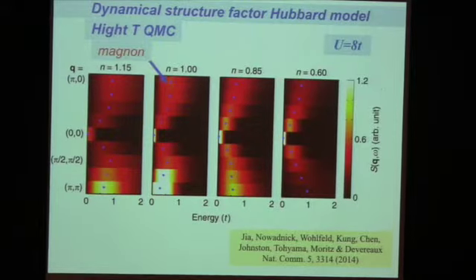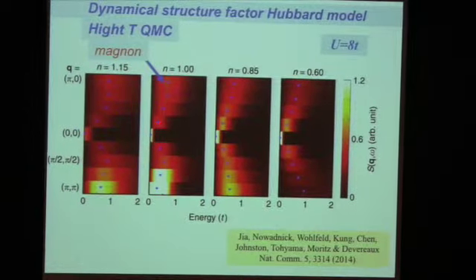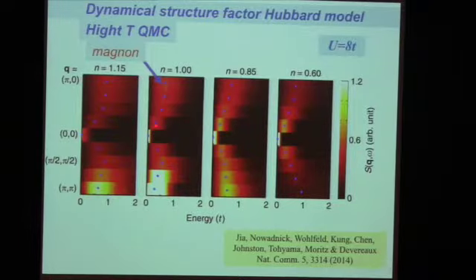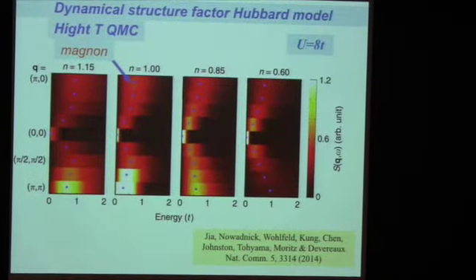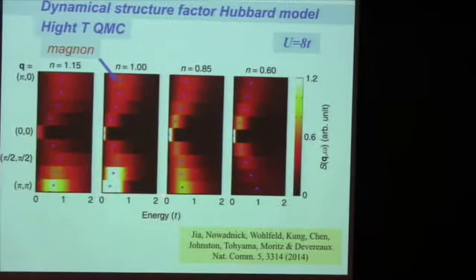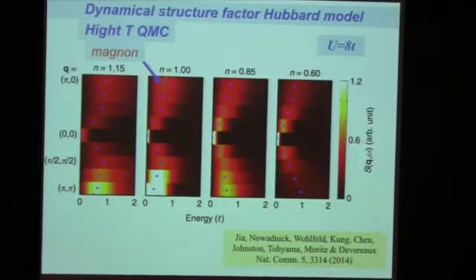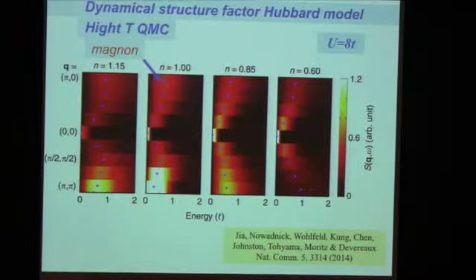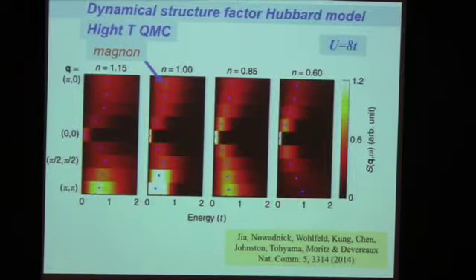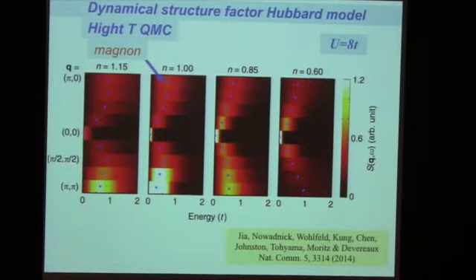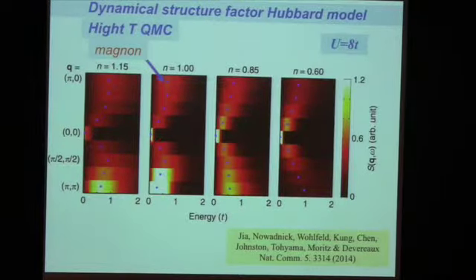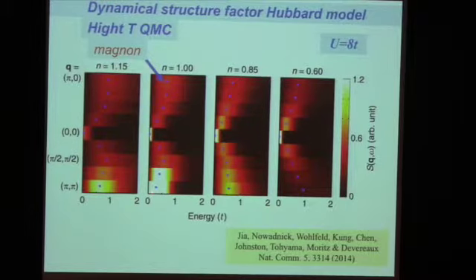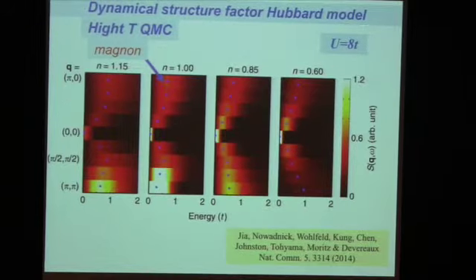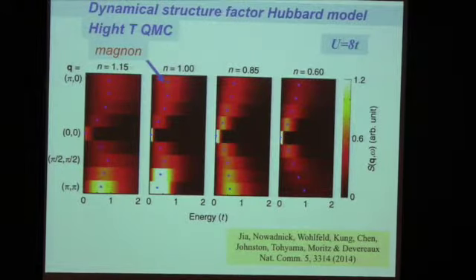Then for the undoped system here, n equals 1, you see that again there are well-defined magnons. Momentum is on the vertical axis, and on the horizontal axis energy. So you see a nicely dispersing branch out here if you go to pi 0, and also when you go to pi half, another part of the Brillouin zone, you see a well-defined magnon until you go to pi, where of course you don't pick up the antiferromagnetic peak, but there is a lot of spectral weight there that is anticipating the antiferromagnetism that will set in at lower temperatures.